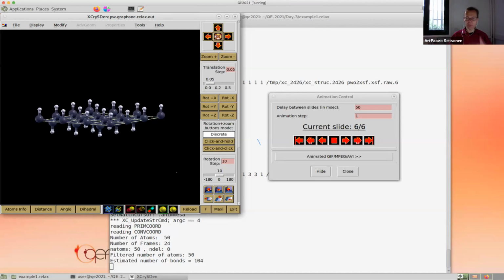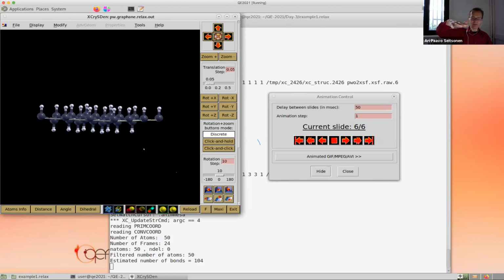Now the question will be, why is this? And I mentioned already something about the chemistry at the beginning. So if you think of sp3 hybridization, that's of course the tetrahedron. Again, in graphene, you don't have anything above or below the plane, and the carbon takes the sp2 hybridization, and it's perfectly fine there. It's a semi-metal. Here we have sp3, so it's like a silicon bulk would be, and so we have somewhat out of plane organization, so that we get a bit closer to the geometry that would be in a tetrahedron.